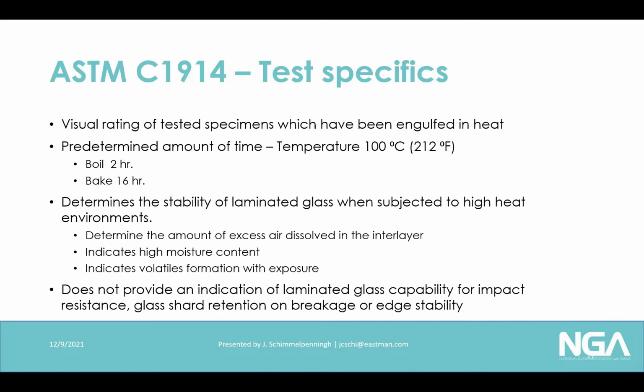The boil is for 2 hours, and what you do is you literally submerge the laminated glass into boiling water for a 2-hour time frame, and then you take it out and rate it. Or you can put it in a 212 degree oven for 16 hours, and then you take it out and rate it. Again, what it does is it determines the stability of laminate glass to these high heat environments. It has always been referenced as the standard temperature and time in ANSI, and also for both the automotive industry and the architectural industry.